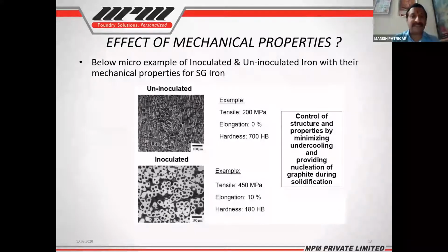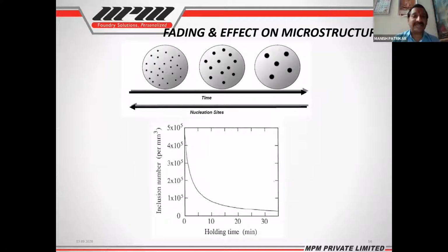Okay. So this is the effect on the mechanical properties. Earlier we have seen the microstructure. Now this is the effect on the mechanical properties, because inoculation also improves the mechanical properties. If you can see in the first and second, it will improve the tensile strength, it will improve the elongation, and will also improve the hardness with the improvement in the microstructure. So this is the fading effect of the microstructure. Holding time versus inclusion numbers.